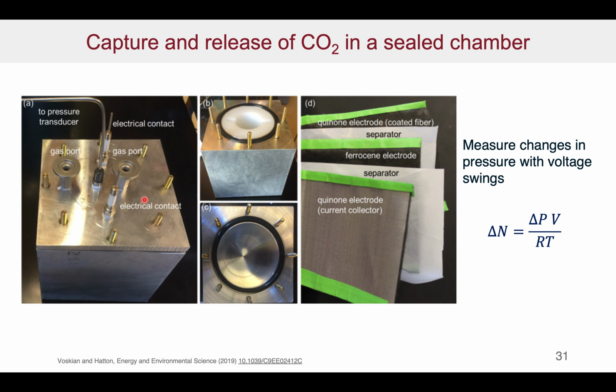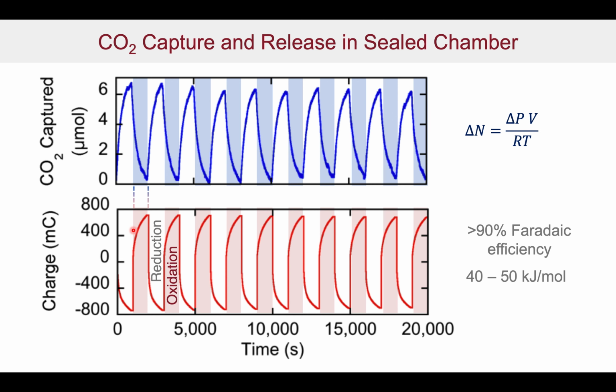We put these in a sealed chamber with electrical contacts, of course, and the sealed chamber is connected to a pressure transducer. We introduce CO2 into the sealed chamber, and when we apply the reduction potential, the CO2 gets absorbed, the pressure goes down, and you can then calculate the number of moles absorbed. When you reverse the potential, the pressure goes back up again. Indeed, we can calculate the amount of CO2 captured from these fluctuations in the pressure. This shows a reduction leg and then an oxidation leg, the amount of charge applied, and the CO2 that's being captured on the reduction side and released on the oxidation side.